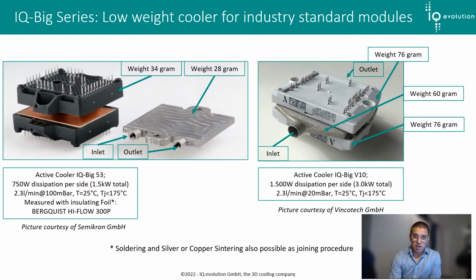What you can see here on the left is a big IQ 53 industrial, which has been evaluated with a temperature of 25 degrees and at 100 millibar and 2.3 liters per minute. For isolation, Bergquist high flow 300P has been used, and we were able to dissipate 750 watts per side. Unfortunately, the pump wasn't strong enough to evaluate further.